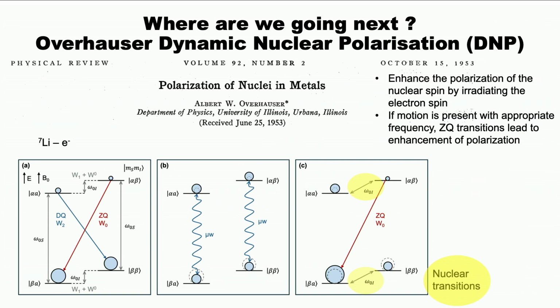And if you looked at the energy levels of a coupled system in lithium, so the lithium is this spin here, and you looked at the electron ones. If you irradiated the electron spin resonance and you had the right relaxation mechanisms, namely this relaxation mechanism was faster than the other ones, you could actually enhance the magnetization of lithium metal. So this was in '53.